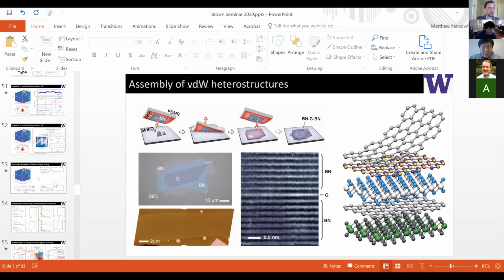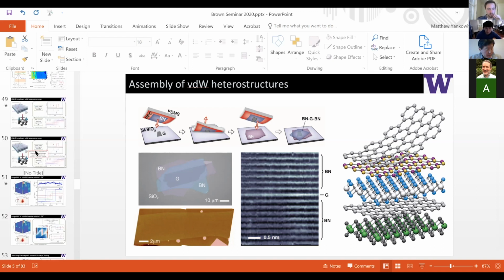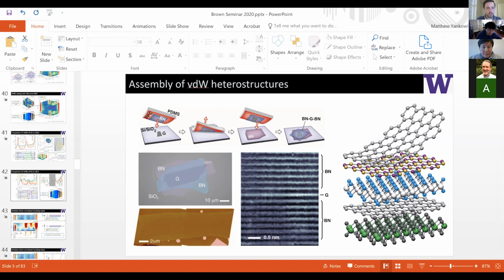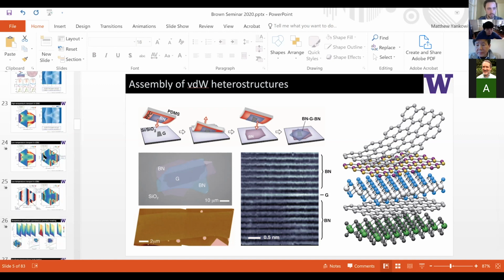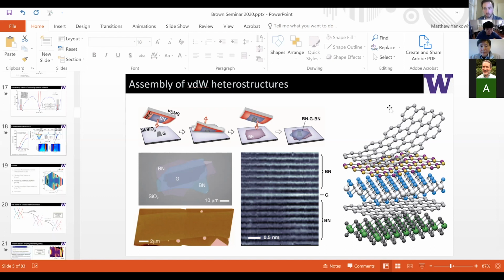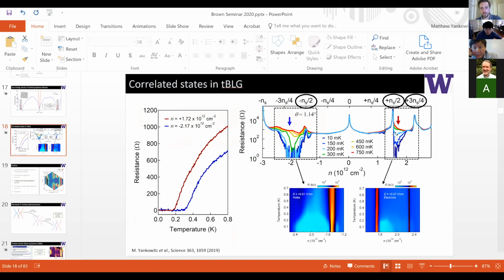So you discussed this orbital ferromagnetism, but I was wondering if there's ever been any discussion of anti-ferromagnetic ordering of these orbital moments. Is there any indication that that might be possible? Yeah, that's a great question. I think that's probably the case in the states at half filling in twisted bilayer graphene. When we measure these states as a function of either perpendicular or in-plane field, we see that they're suppressed. That suggests they're spin unpolarized and therefore likely valley polarized. So there'd be a spin anti-ferromagnet, but valley ferromagnet.